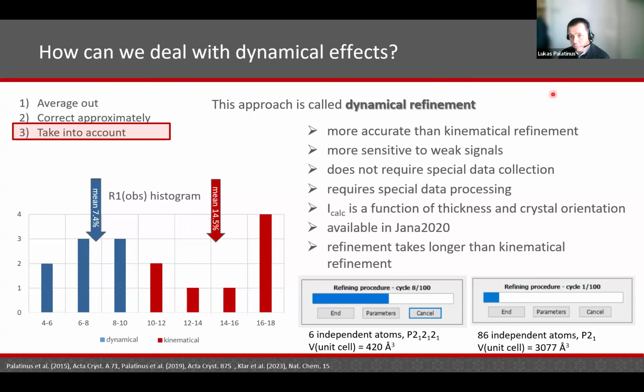But of course, that's just an R factor, that's just a number, but what counts more is the accuracy of the structure model, which is, as we will see, significantly improved. The dynamical refinement is more sensitive to weak signals. And importantly, it does not require a special data collection. So it's possible to apply it to the same data that were collected for kinematical refinement, so there is no difference in the experiment.